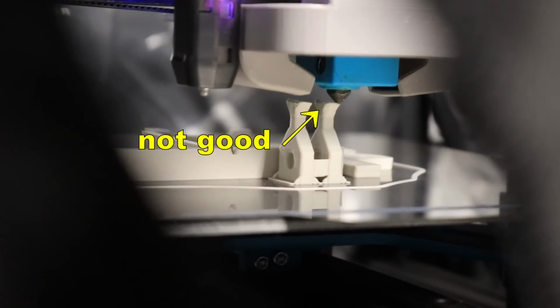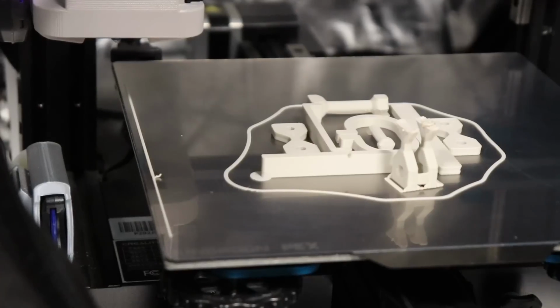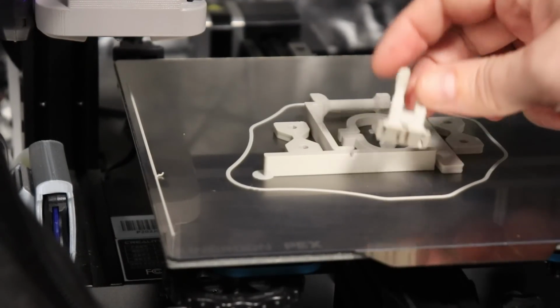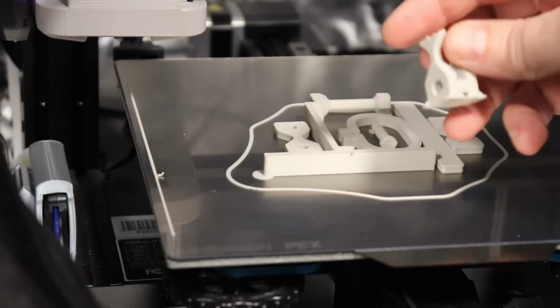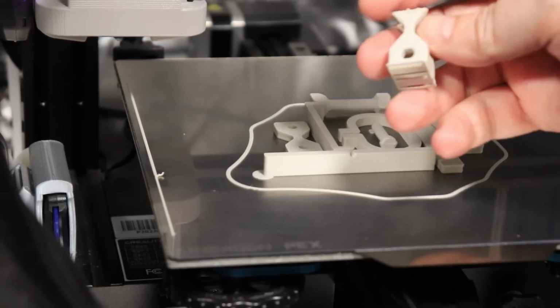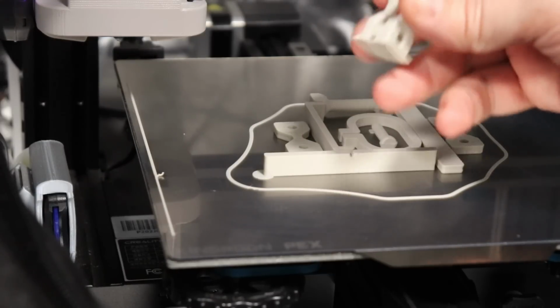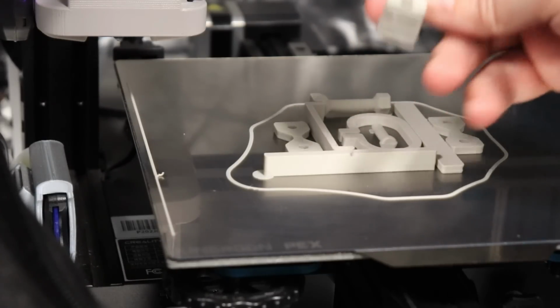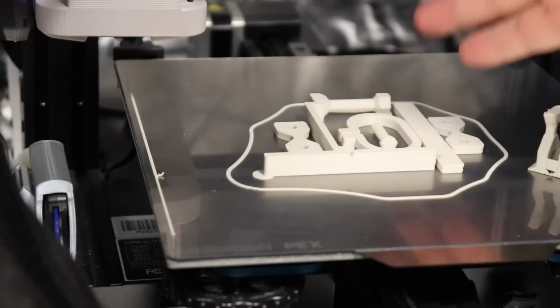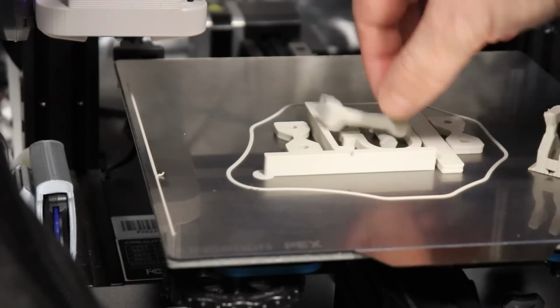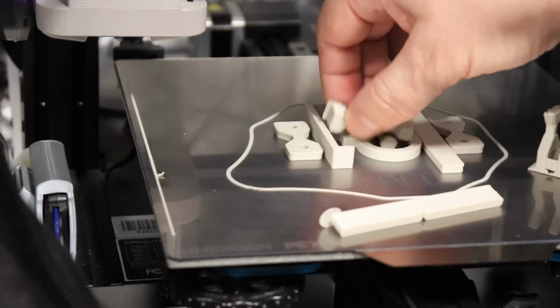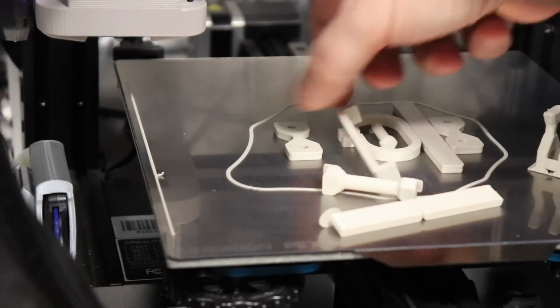I can see the material curls up a little bit. And unfortunately I had to stop the printing because it really curls up too much. So it needs either more cooling, or I have to slow down the printing a little bit here. So these two test objects will be printed again separately, but all other test objects are perfect. And the bed cooled down and it is very easy to remove them from the build surface.